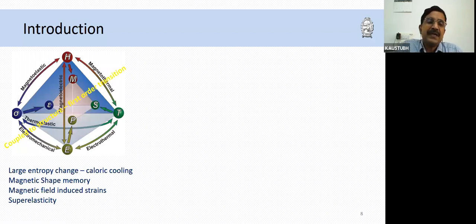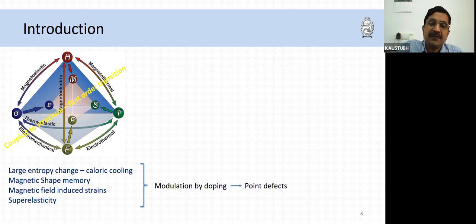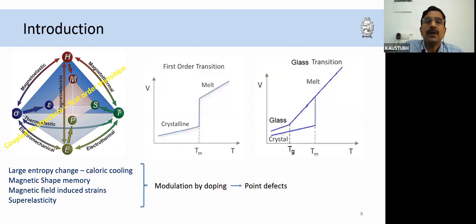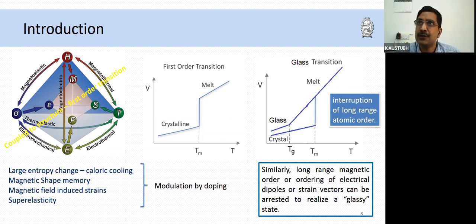Now, what we do is we try to modulate these properties by doping. And when we dope these materials, we also introduce point defects. As we know, suppose I take a melt to crystalline phase transition, then if I introduce defects in this transition, I will be able to slow down the dynamics of this transition and eventually come to a glassy state. And glass is basically a state with a short range order, or we can say that the long range atomic order, which is there in a crystal, is interrupted. Similarly, you can dope defects and interrupt the long range magnetic order or the order of electrical dipoles, for example, and create corresponding glassy states.